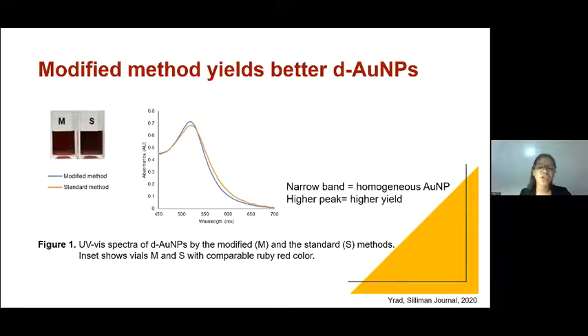Figure 1 shows the reduction products and the corresponding spectra of trials M and S for the modified and standard methods, respectively. For the same reaction composition, trials M and S produce comparable ruby red colloidal gold. It is noteworthy, however, that the spectral band of trial M is narrower and showed a higher peak, higher absorbance at 500 nanometers, compared to trial S. According to previous reports, a narrow band means homogeneous gold nanoparticles, and a higher peak means higher concentration and therefore better yield.